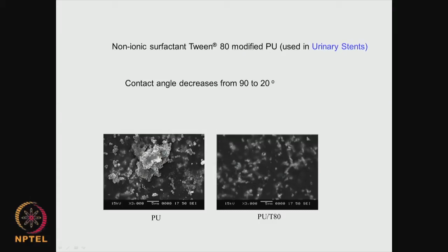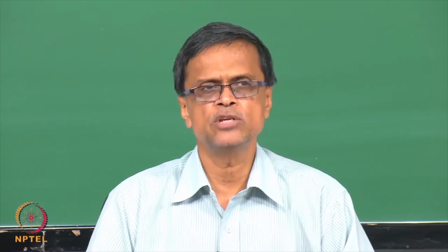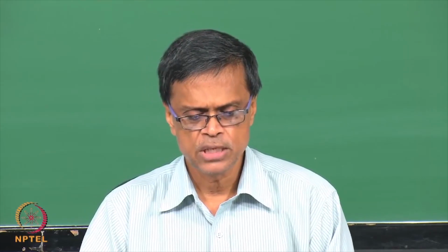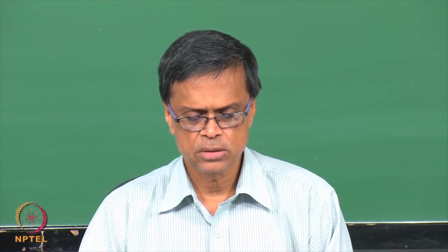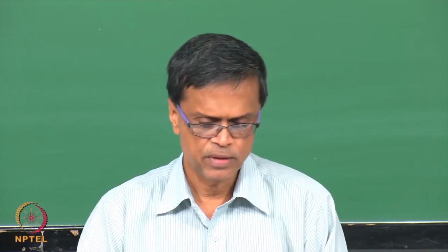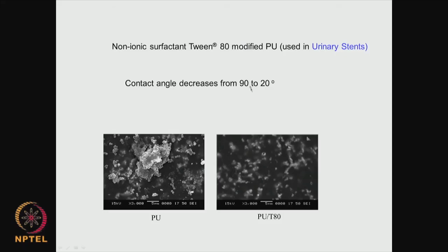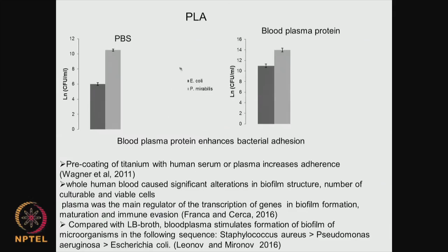bacteria. These amphiphilics do not have an antibacterial effect, that means they do not have a killing effect, but they are able to prevent the attachment because they have reduced the contact angle from 90 to 20. That means the surface energy increases, or the material has become more hydrophilic once you immobilize these surfaces with this particular non-ionic surfactant. That is another approach. Let us look at another thing.